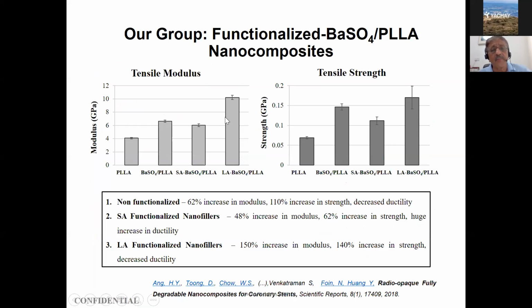Another way to address the problem of strut thickness is to develop nanocomposites. We are also doing this work now using nano fillers, which are also radio opaque. So I mentioned that all of these stents have to be radio opaque so that they can be seen in the X-ray. And we do this now by actually using barium sulfate or tantalum or other particles that will increase the mechanical strength while at the same time improving the radio opacity of these stents.